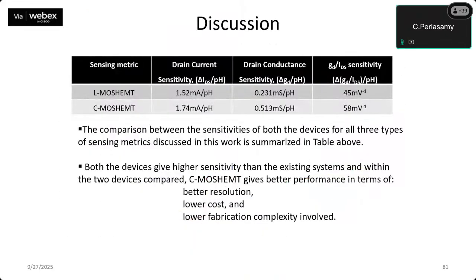So that conclusion is that we have calculated the sensing metrics. The planar structure sensitivity in terms of current is 1.52, and the circular pattern sensitivity in terms of current is 1.74. One can also conclude that the fabricated structure is suitable for pH detection.